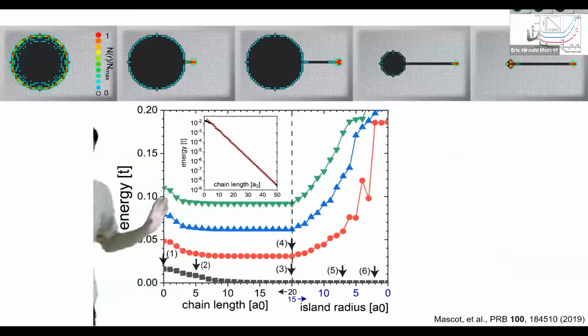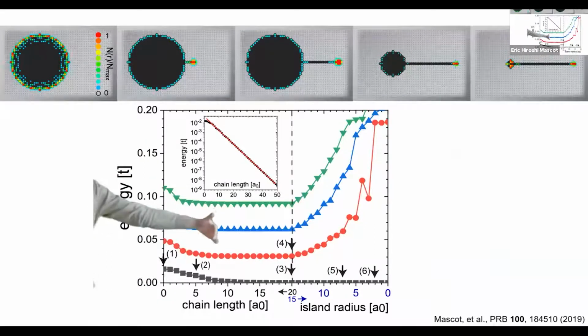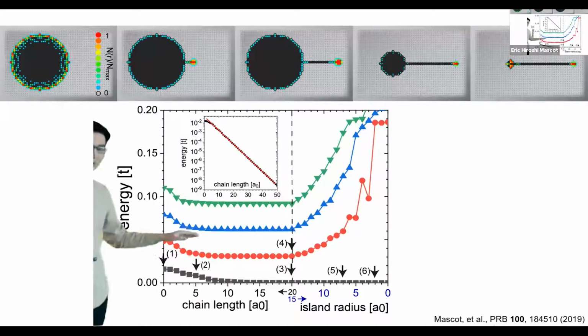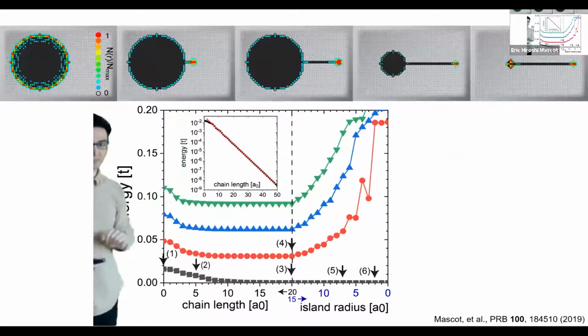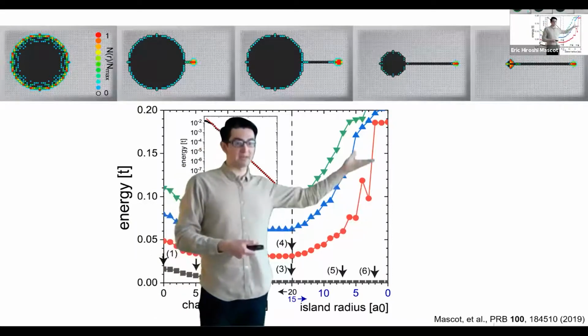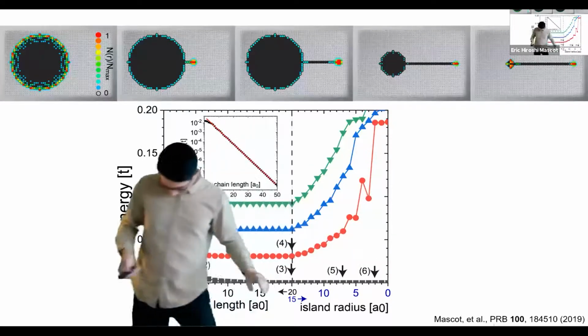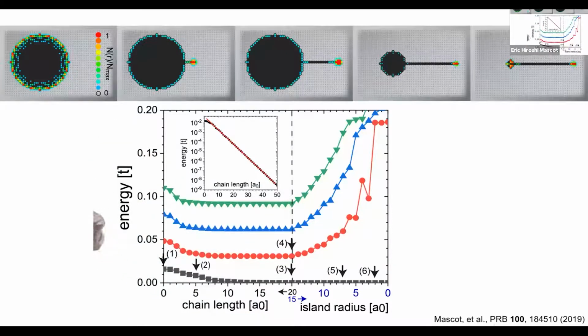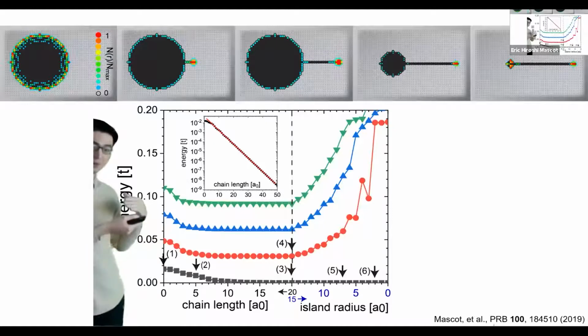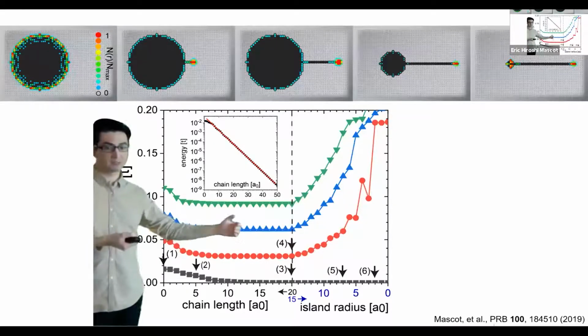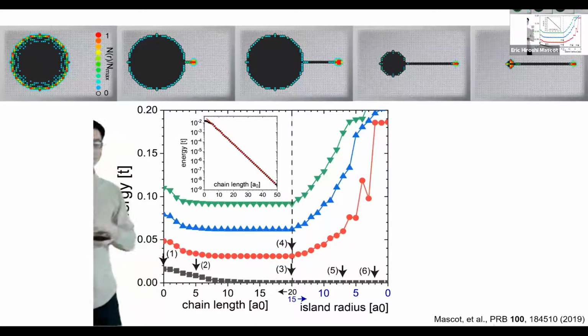And we can look at the energy spectrum as we go through this transition between two-dimensional and one-dimensional Majorana bound state or zero modes. And we see we have our edge mode, which is like evenly spaced energies. And once we start shrinking the island, the edge band gaps out and the zero mode remains. And one particular feature of this is that there is no bulk energy gap closing. So since we don't close the energy gap, that means that we don't have a phase transition while we do this, going between the two different Majorana zero modes.